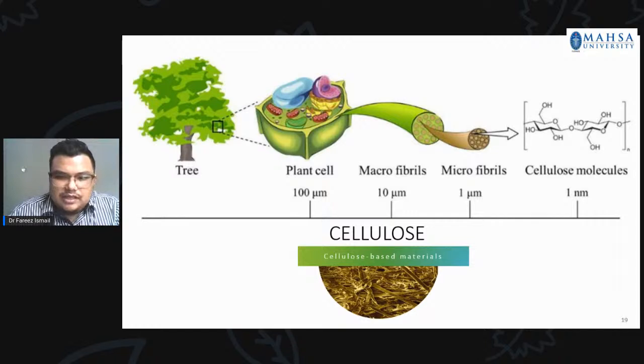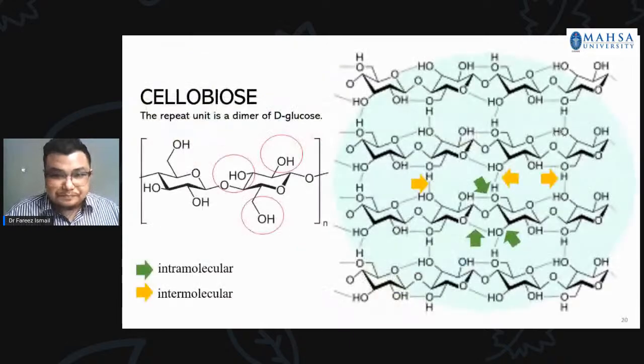The fiber contains, as I mentioned, crystalline and amorphous regions. The amorphous region is preferably degraded to release nanoscale components of nanocellulose, because it's prone to react with other molecular groups that may disrupt its property. So the cellulose is composed of a unit we call cellobiose. It's a dimer of D-glucose. And these linear D-glucopyranose units are linked together by beta 1,4 linkage to produce a crystalline structure of cellulose known as elementary fibrils. So this is elementary fibrils.